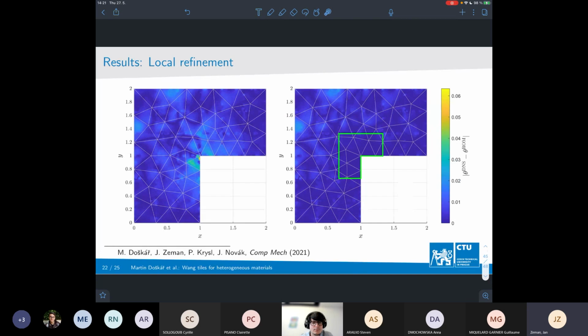And with it, what is even more convenient about the framework and about how Martin actually formulated all this is that it allows for a complete local refinement. So, for instance, in this reentrant corner, which is known to be troublesome and in which you've seen that most of the errors are localized, you can switch to fully resolved microstructure on the fly and get these errors in this region under control. So this is again something which we like very much about this scheme.